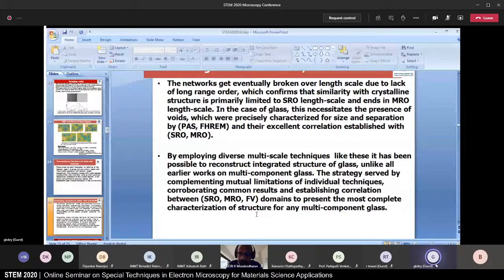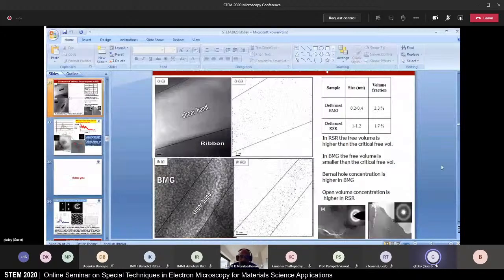So I have just 2 more slides just to show the application of this. The first thing that we would like to apply is studying defects, that is defects in glasses. This is an example of how the defects look like, and these are actually voids inside the region which is having defects, and the voids are much more in density here compared to the adjoining region. This kind of information was not obtained earlier, and here again we have voids. This is in a bulk glass and this is in a rapidly solidified glass. You can see the difference in the density of voids and the distribution of voids.